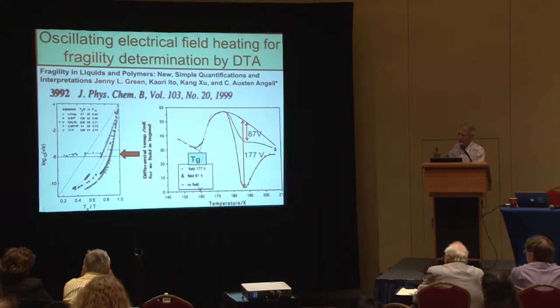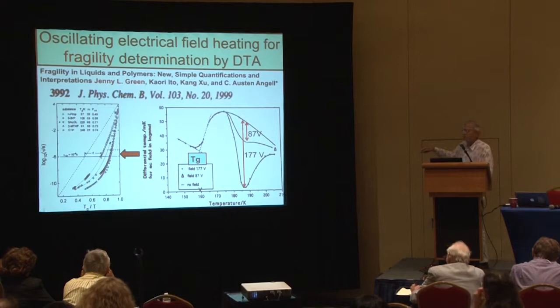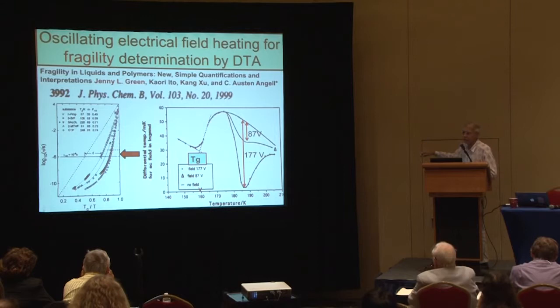Now, this is a bit of a digression, but I want to draw attention to something quite cute that Jenny Green, who was in the audience here, helped us with. When we were trying to determine the characteristics of the viscosity of liquids which have, and I think Brian mentioned this, a tremendous range of values as the temperature goes from melting points down to the glass transition temperatures. They execute 15 orders of magnitude. So the frequency which would give maximum heating near the melting point is 15 orders of magnitude wrong for giving maximum heating near the glass transition temperature.